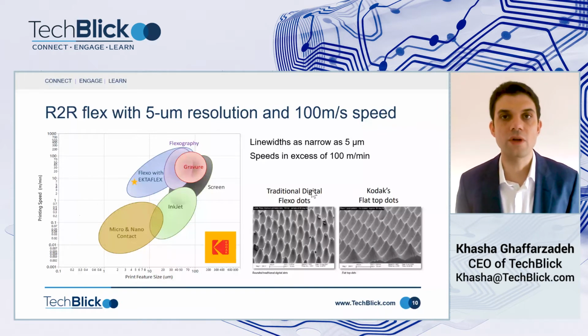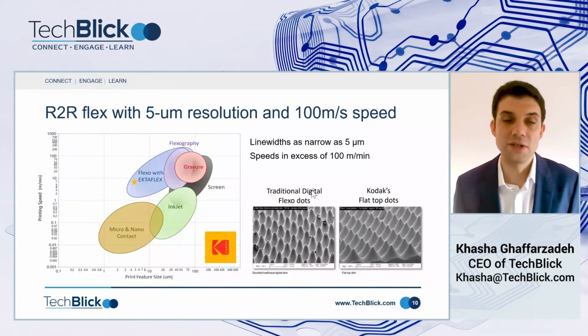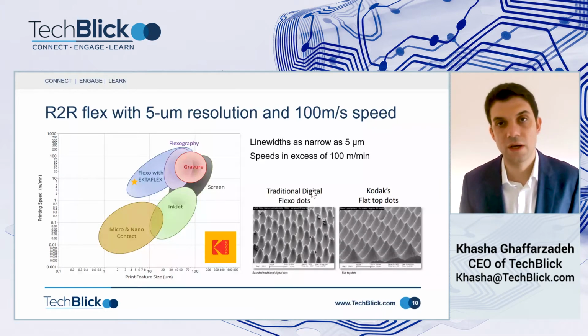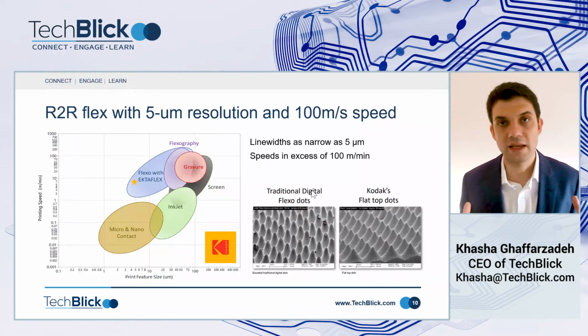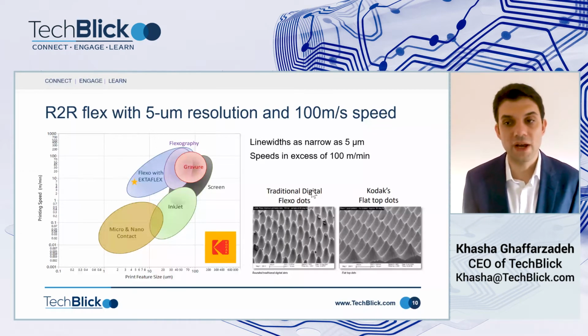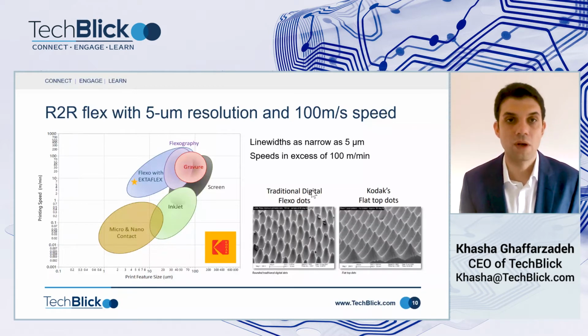Now this example by Kodak, again one of our sponsors, shows that one can do roll-to-roll flexo printing, achieving a line width resolution of 5 micrometers while running the process as fast as 100 meters per minute. And this is very interesting. As you can see on the bottom right-hand side, some of the innovation has to do with the way they form their master templates. One of the key points is that the way they manufacture it, the dots have an actual flat top. So a very interesting process in my view, with very interesting applications.